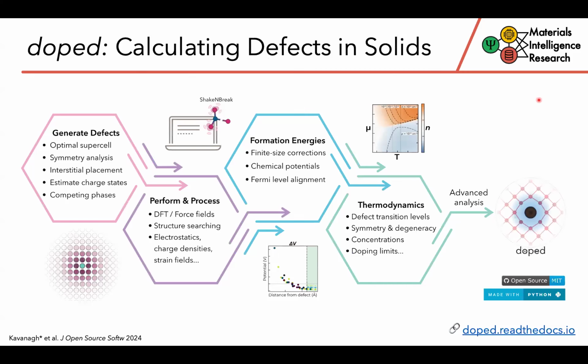Okay, so moving on, I just wanted to briefly mention this toolkit Doped, which I've developed, which is essentially a comprehensive defect simulation package, which provides a robust platform to manage the full defect simulation workflow, all the way from efficiently generating and enumerating defects in an appropriate supercell and their potential charge states, through to generating input files for our calculations and parsing the results, performing various types of finite size corrections, computing chemical potentials and their associated limits, and then through to full thermodynamic analyses, so looking at defect concentrations under a range of different possible synthesis or treatment conditions, doping limits, and more.